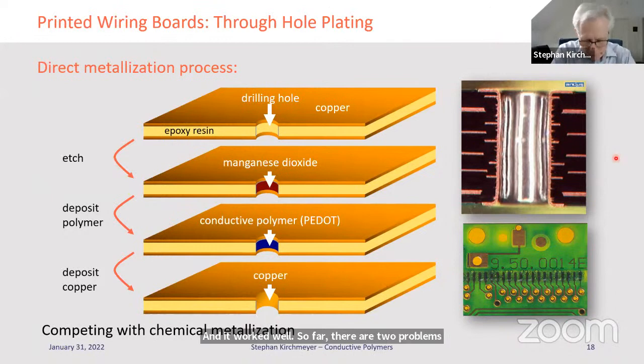First of all, palladium is expensive, and people did not like to use this material too much. And the second was these metallization baths were pretty unstable against any contaminations, and it could easily happen that such a bath is not doing what it's supposed to do. And it was difficult to steer these processes and to make them work for a very long time without having much material wasted.